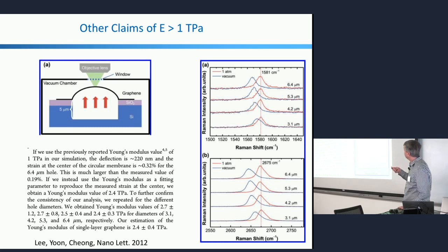Here's another claim using Raman spectroscopy, where you take a membrane and you let it balloon in and out, and you look at the Raman shift, which is a very nice experiment, well done. The shift in the Raman modes as a function of pressure. The nice thing with hydrostatic pressure is that you know the shape of the membrane very well. It's a nice, very controlled experiment, but if you're using the Raman modes to calibrate the strain in the membrane, you have to know the shift in Raman modes with strain. That may not be as well understood as thought. In any case, again, now we get 2 terapascals.